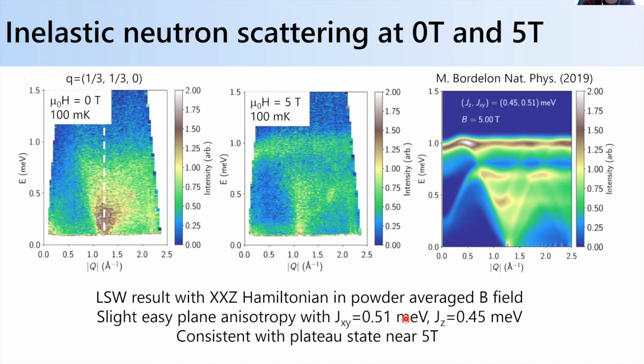But there are anisotropies in the single crystal studies, which have been done on slightly different systems, but that should have roughly similar phase diagrams, which I'll talk about in a second. I would say that those are probably a sharper place to start than trying to infer anything deeper from the powder data, because we started looking at sodium ytterbium O2 and then we really focused on trying to make crystals of this because the oxide has just the cleaner physics. It's just larger crystal field splitting, larger charge gap, everything, right? But ytterbium oxide is just a bear to deal with.